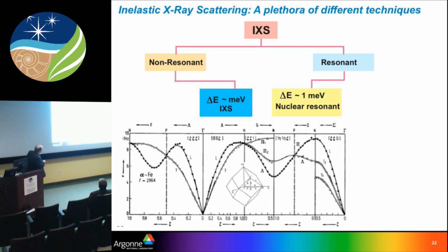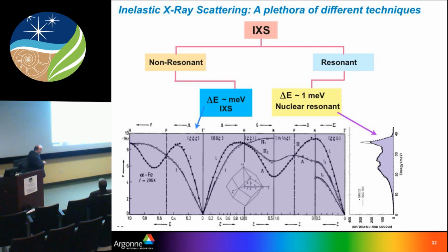The dispersion-free points where you cross the Brillouin zone boundaries correspond to these peaks. Even if you don't make these measurements one by one and simply measure this very quickly, you can still get where the transverse and the optical modes hit the Brillouin zone boundaries. So these are pretty good indicators of where the mode frequencies are at the zone boundary.